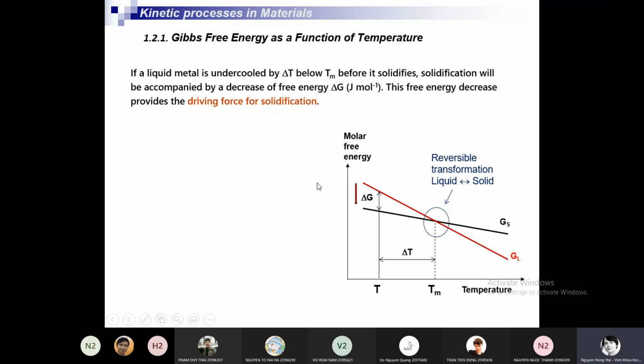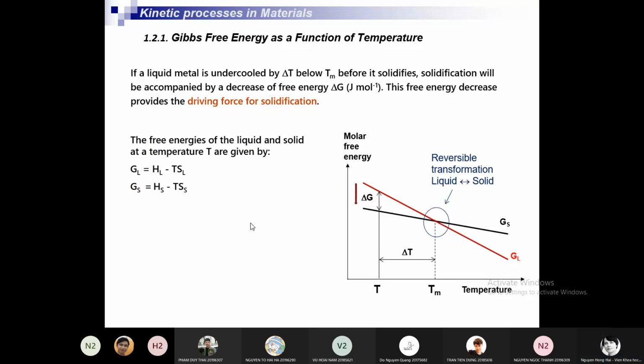The free energy of the system decreases, so we can calculate this decrease in free energy. The free energy of the liquid is equal to enthalpy of liquid minus T multiplied by entropy of liquid, and free energy of solid is equal to enthalpy of solid minus temperature multiplied by entropy of solid.